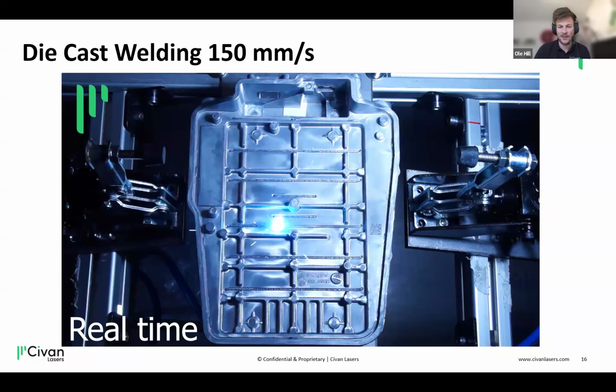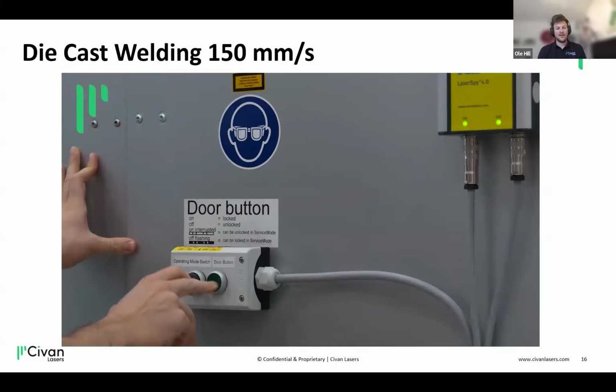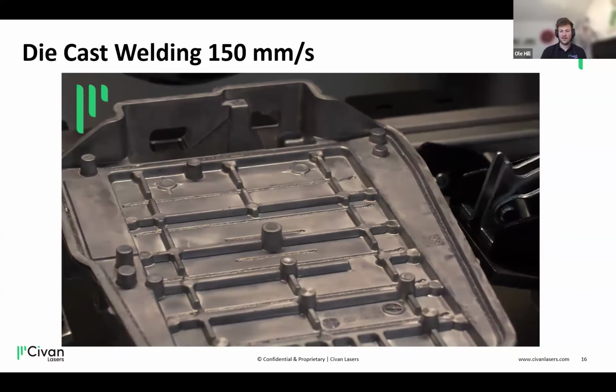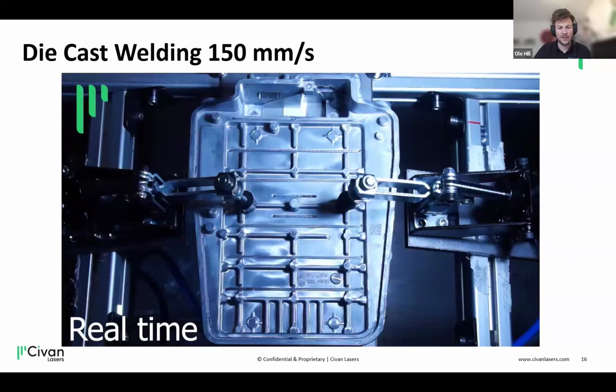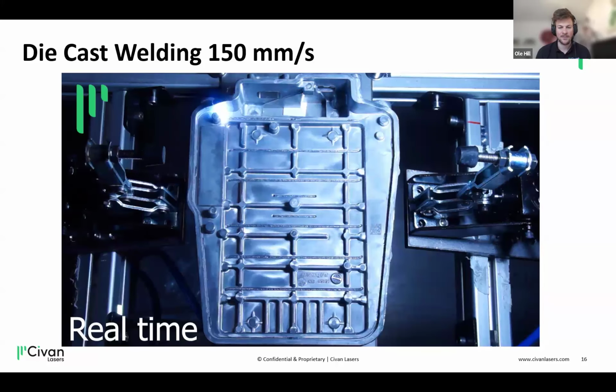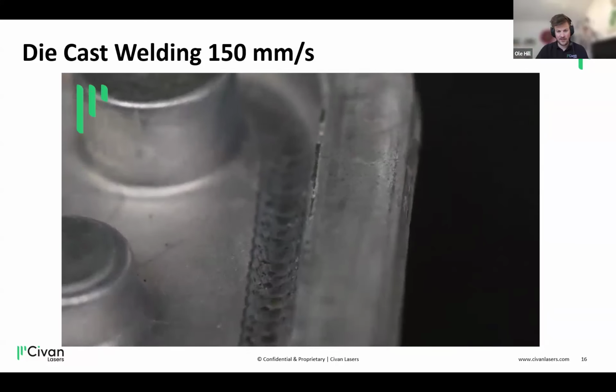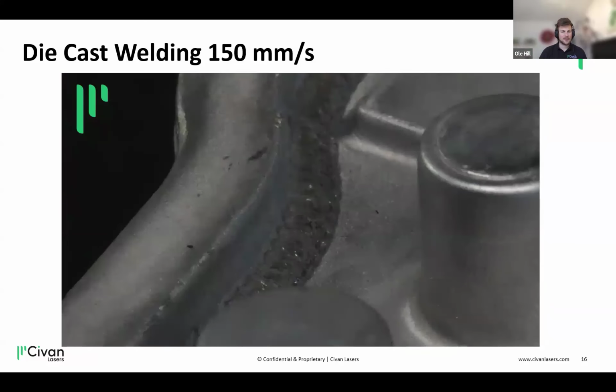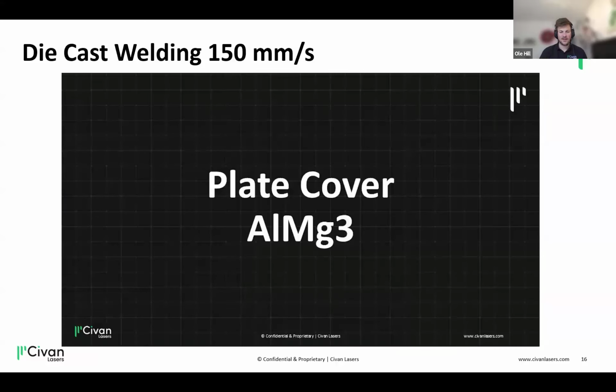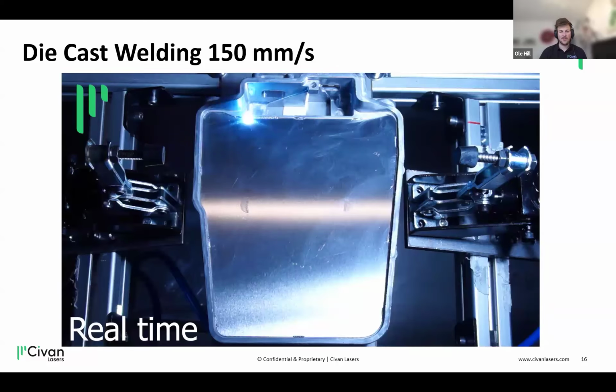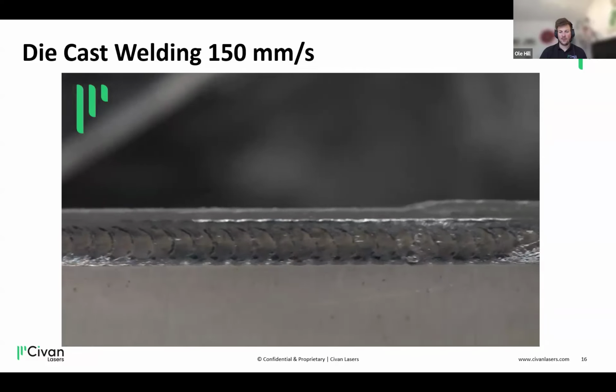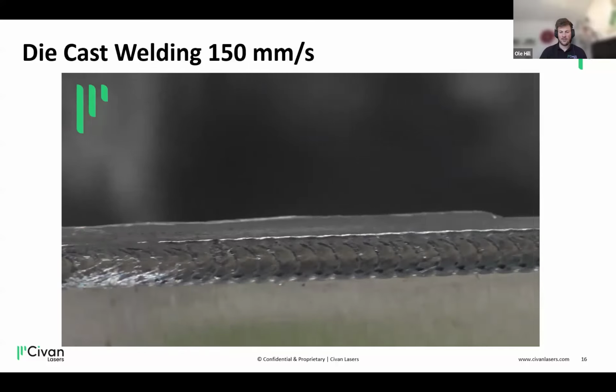Here I brought you a video from our lab in Hanover. I'm just going to let it play. It's welding in real speed, so you get an impression of what 150 millimeters per second can mean on a workpiece, which is the size of a normal notebook, for example. Now here you see a close-up video of the weld seam. This is done with two passes to get this nice surface finish. And this is the example I told you about: instead of using a cast cover, you use a wrought alloy. That makes it a lot cheaper.